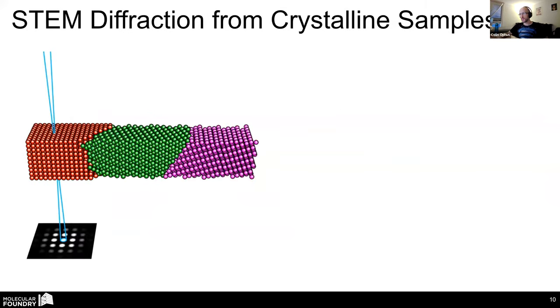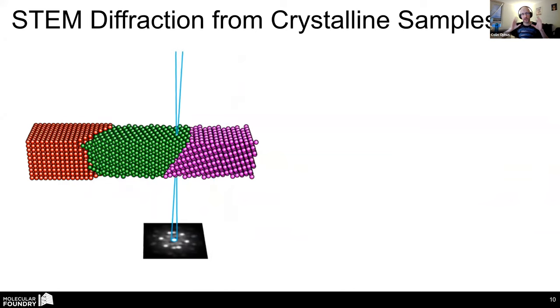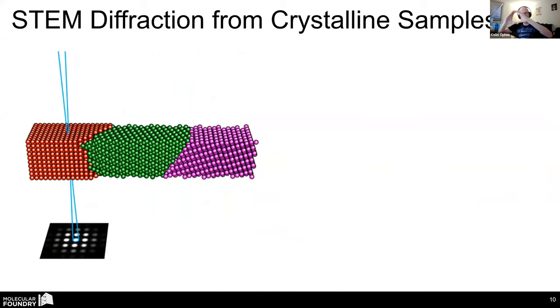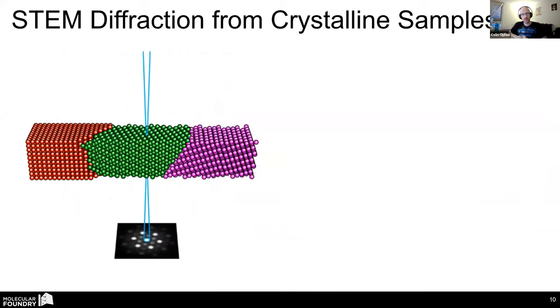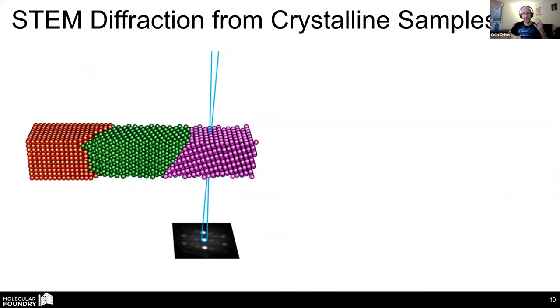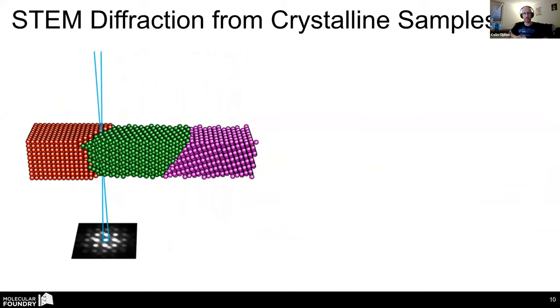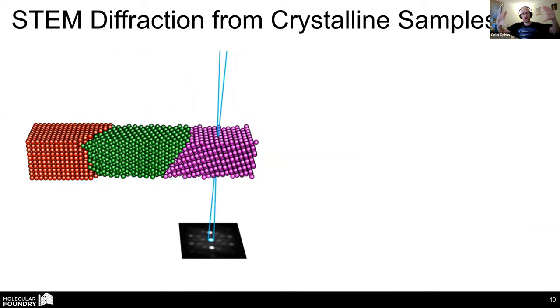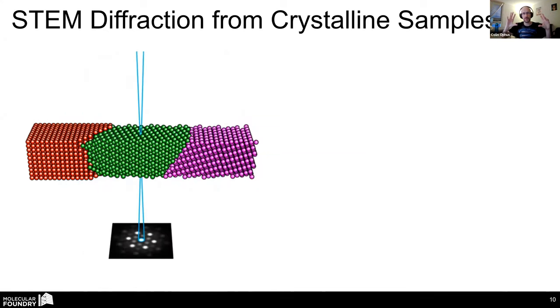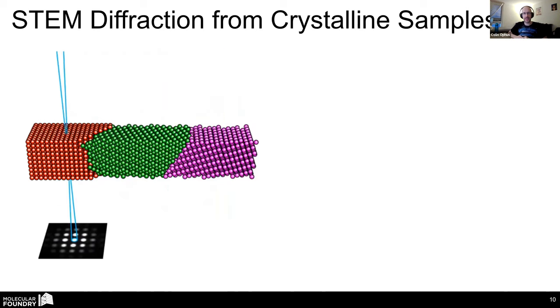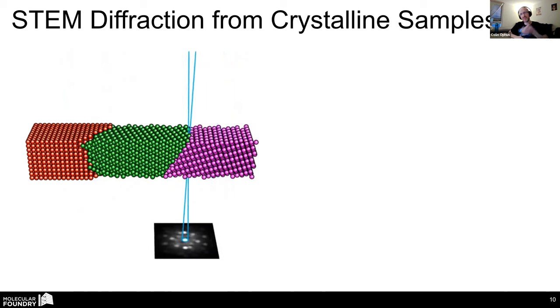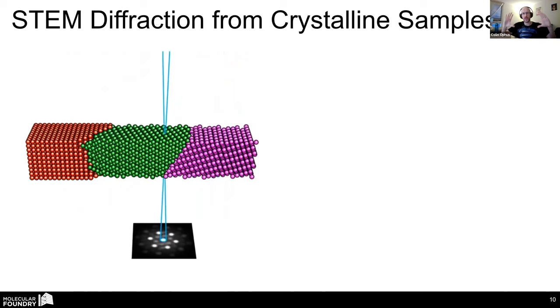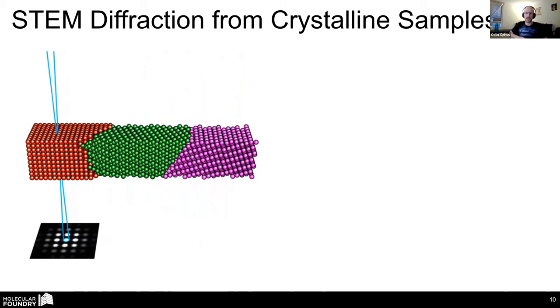If you want to do atomic resolution imaging, you can show mathematically that if you have your center spot and your diffracted spot, when those spots overlap and create interference between the adjacent diffraction disks, that's where the atomic resolution scattering comes from. And so if you want atomic or subatomic resolution, you want a very large convergent semi-angle, usually on the order of 15 or 20 milliradians. That would be the current generation of microscopes. Next generation aberration correctors will let us push it out to 30, 40, 50, maybe even 60 milliradians.